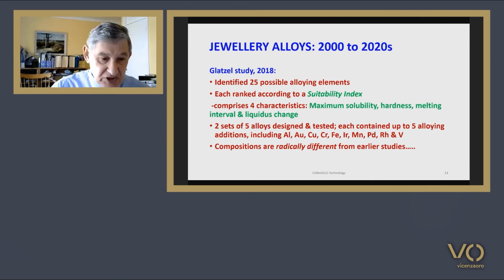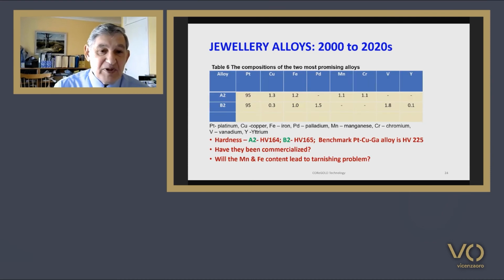The compositions they studied are radically different from those alloys we've seen in the earlier slides. The compositions of the 2 most promising alloys are shown here on the table. A2 contains copper, iron, manganese, and chromium. The second alloy contains a little bit of copper, iron, palladium, vanadium, and yttrium.